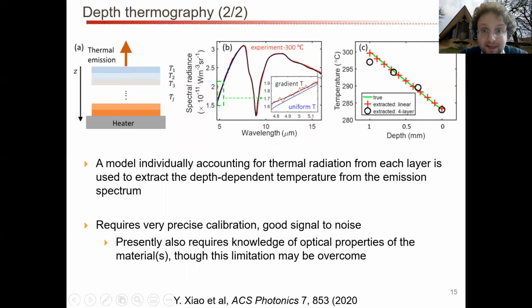If you look at the experimental data and you look at a model that we built, for example, if you just apply Kirchhoff's law and Planck's law with the known emissivity, you will find that the two curves match up really, really well, except in this region over here at very short wavelengths, between 5 and 6 microns, where this blue curve, this model, deviates from the experiment. And you might look at this and say, well, of course, this is just experimental error. Look, you can't even see it on the plot. You have to zoom all the way in to be able to see it. However, it turns out that this difference is actually quite meaningful, because in the region at 5 or 6 microns, the fused silica becomes semi-transparent.